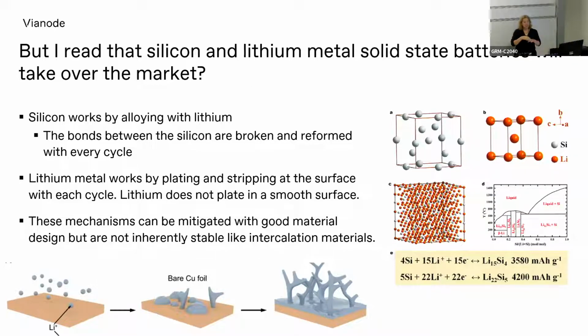So you have entirely broken all of the bonds between the silicon atoms, which means that every time you push all of those lithium atoms in and pull them back out, all of those silicon bonds that have been broken have to come back in exactly the same way, in exactly the same structure, in order to maintain the material the way that it was built. And that's pretty unlikely to happen.